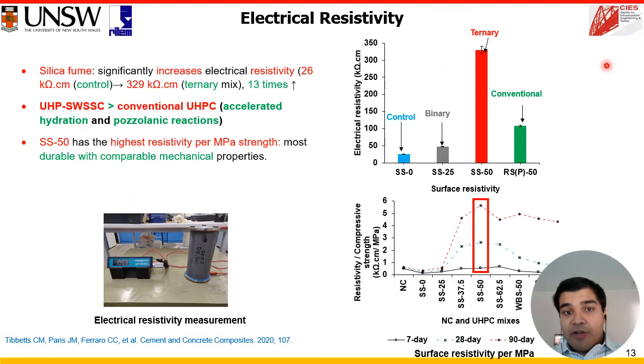We performed a non-destructive test of electrical resistivity and found that the ternary mixes, the OPC, slag, silica fume based mixes, produce significantly higher electrical resistivity compared to control. When compared to conventional UHPC, the marine UHPC produces considerably higher electrical resistivity.